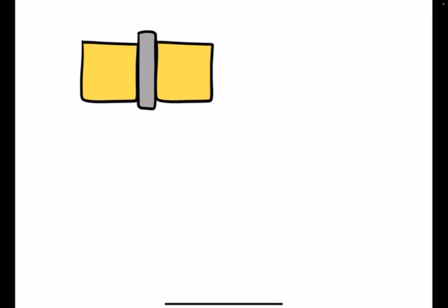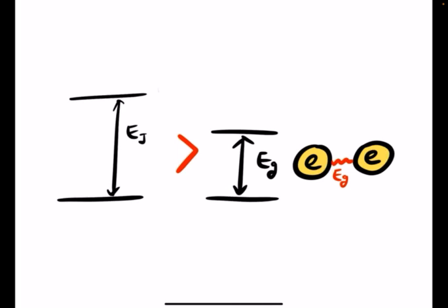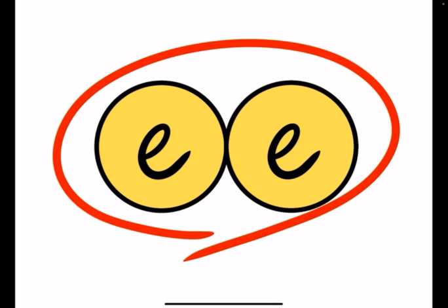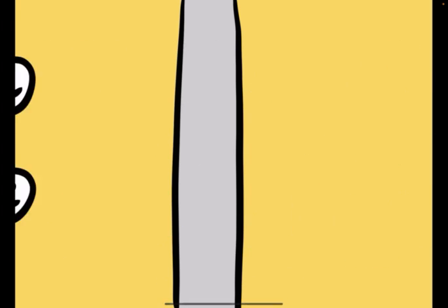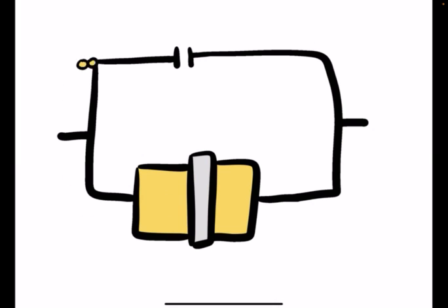Now, Josephson junctions consist of a metal-insulator-metal sandwich, typically composed of aluminium superconductors and an insulating aluminium oxide. This structure is essentially two superconducting electrodes separated by a very thin tunnel barrier. The insulating material in the Josephson junction has an energy gap greater than the typical energy difference between the two levels in a qubit, so the Cooper pairs do not break and the quantum coherence can be preserved. Meanwhile, the insulating layer is very thin, by a few nanometers, which allows effective tunneling through the insulator. When the Josephson junction is connected to regular linear capacitors, the circuit can now create an LC resonator, which can behave as a qubit.